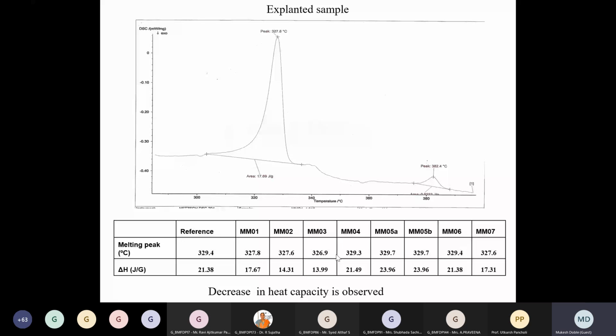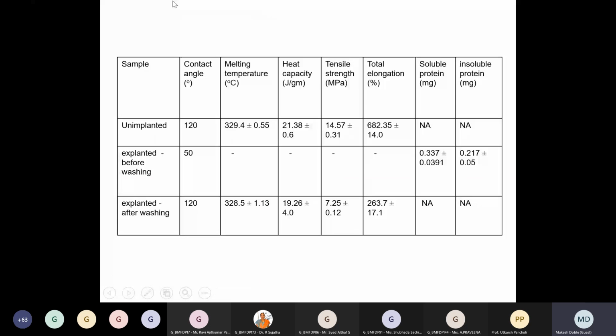As you can see, the reference is the control, that is the polymer before getting implanted. Heat capacity is 21 joule per gram. It's come down to 17, 14, like that. Heat capacity has come down with different samples. Then we looked at the contact angle, which tells you the surface energy of the material. The higher the contact angle, the lower the surface energy. It's more hydrophobic. The lower the contact angle, the more hydrophilic.